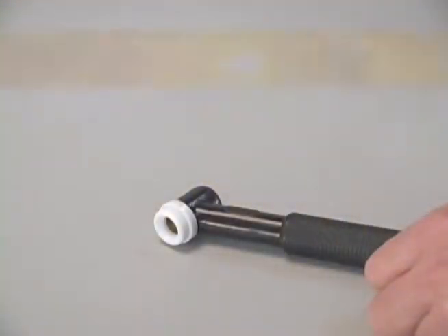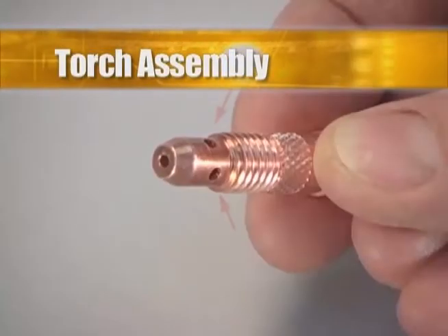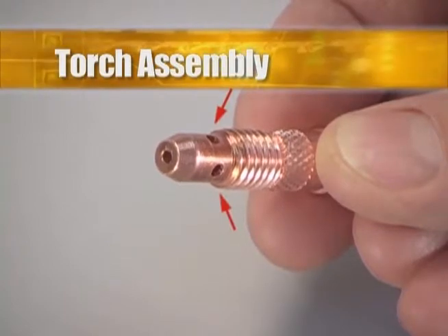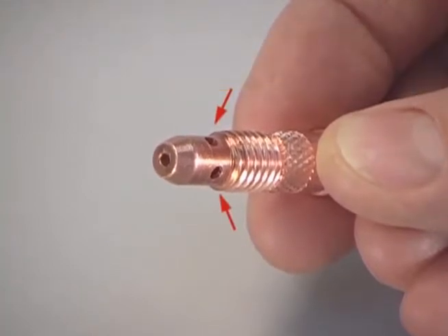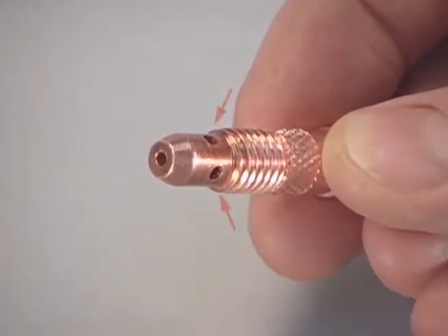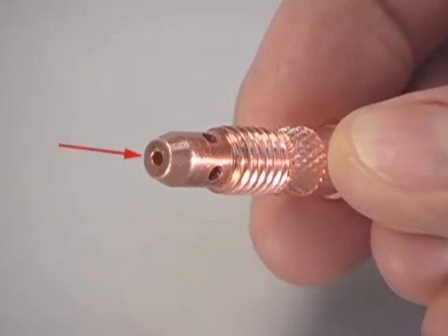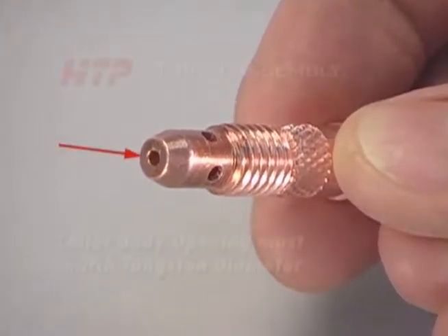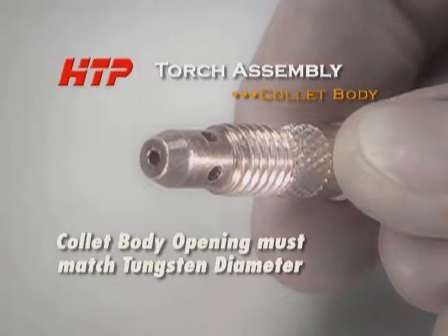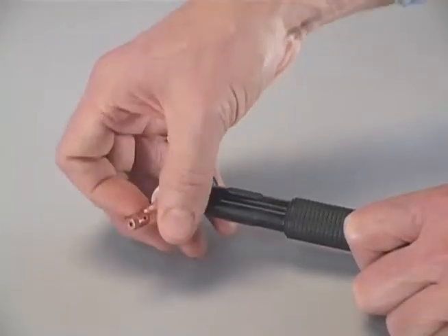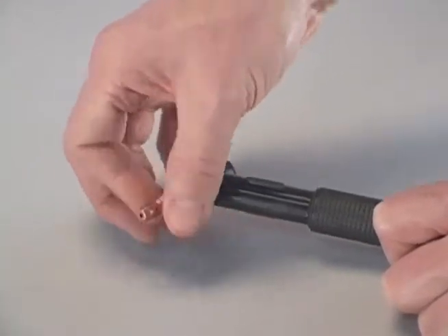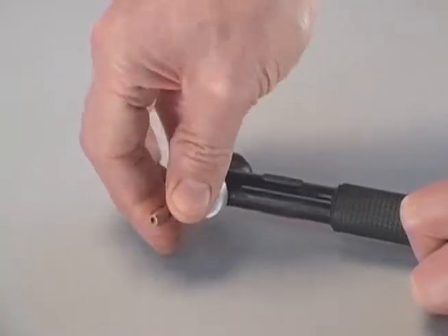Now let's assemble a TIG torch. The collet body has holes that allow the shield gas to flow out from the torch head and around the tungsten. The collet body also has a hole at the front that matches the tungsten diameter. So if we were using a 3/32 tungsten, we would need a 3/32 collet body. Thread the collet body into the front of the torch and tighten snugly by hand.